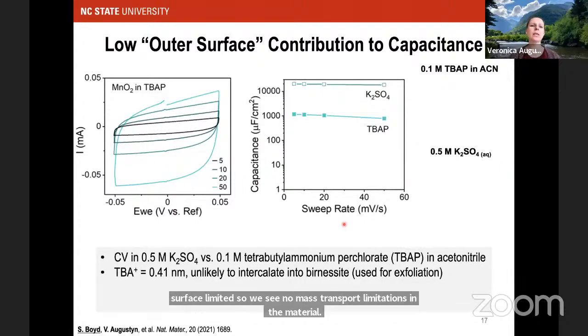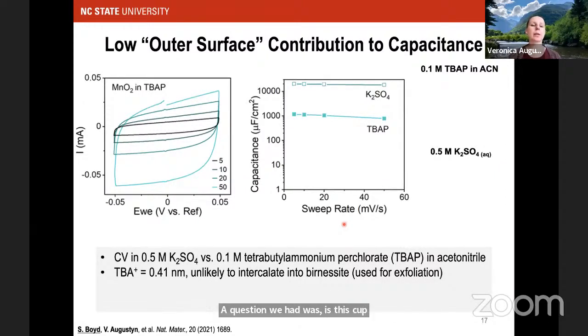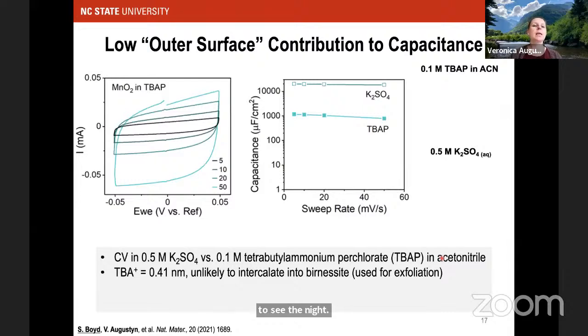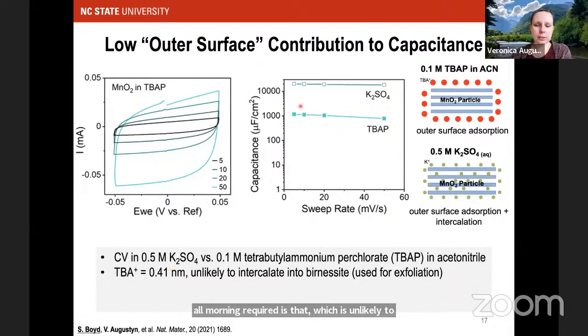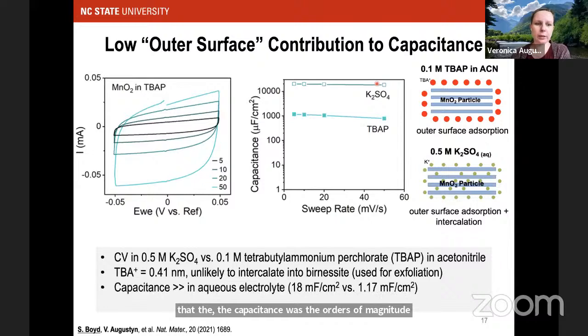A question we had was, is this capacitive response just coming from the outer surface of the particles? So to determine whether that was the case or not, we cycled the material in a bulky cation electrolyte like tetrabutylammonium perchlorate in acetonitrile, so there were also no protons present. And what we found when we cycled it in this tetrabutylammonium perchlorate, which is unlikely to intercalate into birnessite because it's so large, is that the capacitance was orders of magnitude smaller than when we cycle it in an aqueous neutral pH electrolyte.